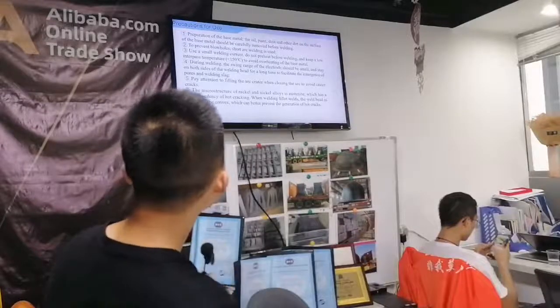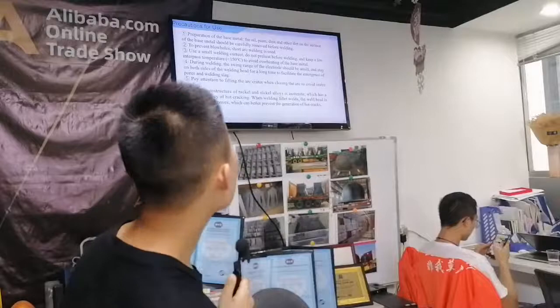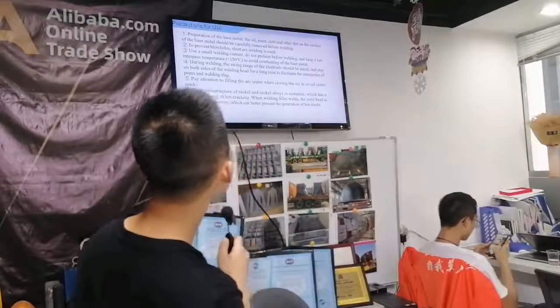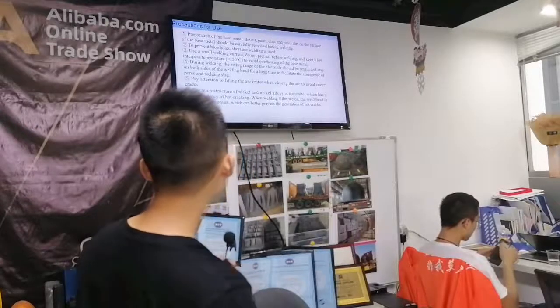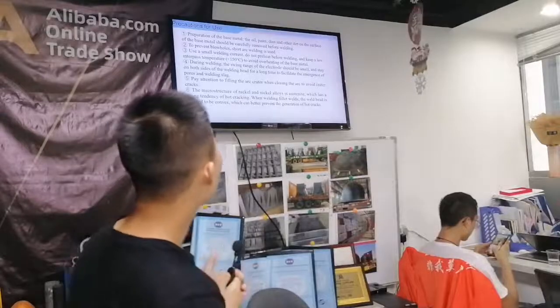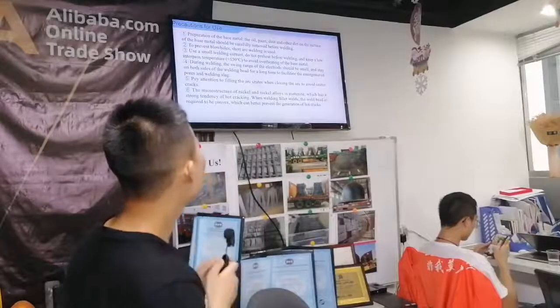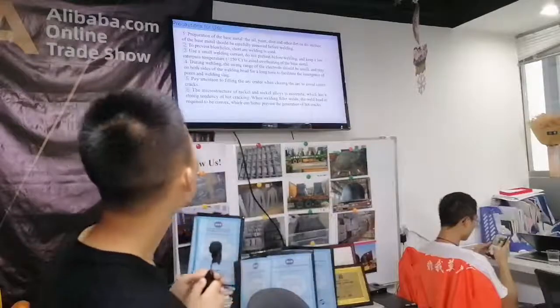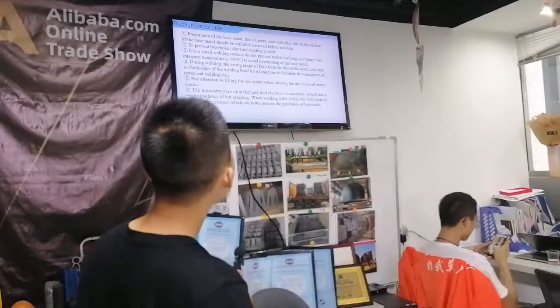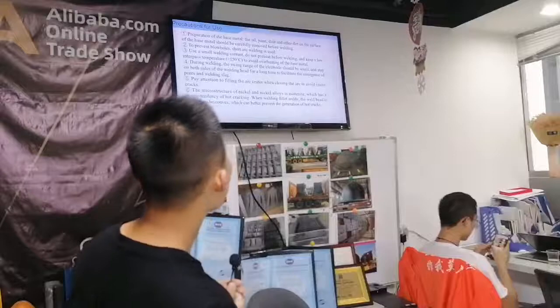Next is preparation for use. One, preparation of the base metal: the oil, paint, dust, and other dirt on the surface of the base metal should be carefully removed before welding. Two, to prevent blowholes, short arc welding is used. Three, use a small welding current. Do not preheat before welding and keep a low interpass temperature, less than 150 degrees Celsius, to avoid overheating of the base metal.